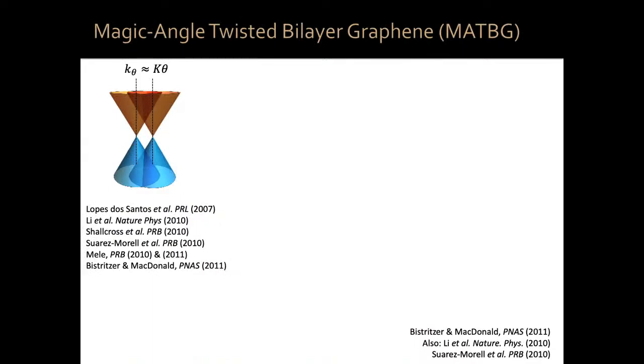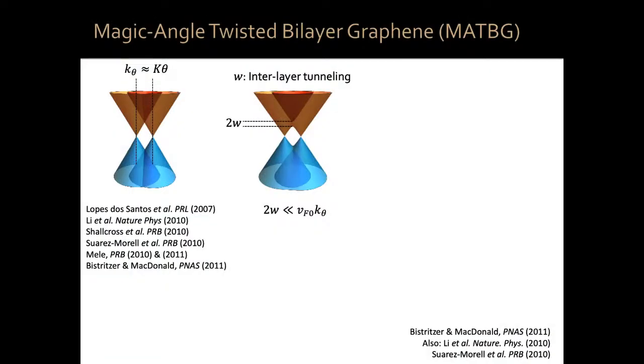So this is the electronic structure, the Dirac cone from layer 1 of graphene, from layer 2 of graphene. They're separated by something proportional to the angle. And this is what would happen if the electrons in one graphene sheet did not know that the other graphene sheet exists. However, when we put these 2 graphene sheets on top of each other, they're only 3 angstroms apart. So the electrons are very much aware that they can go from one graphene sheet to the other. They can tunnel between the two sheets. And that tunneling leads to the following. At that point where you have band crossing, you open a gap due to this interlayer tunneling.